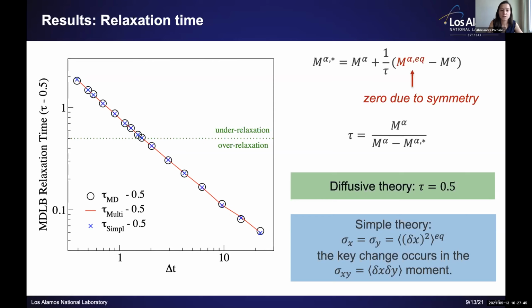We also plotted a simplified theory where the X moment and the Y moment are equal to the mean squared displacement, and only the off-diagonal moment is changing, and we see basically the same results. So the key change occurs for the over relaxation in this moment. That's the main important part.